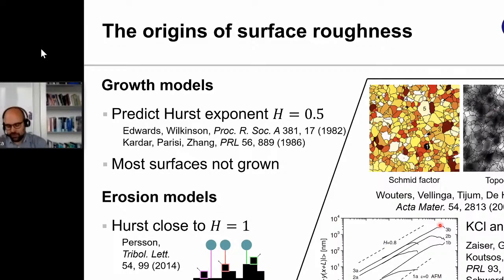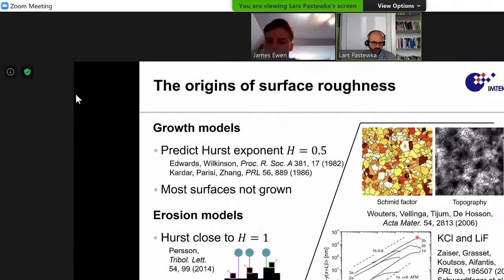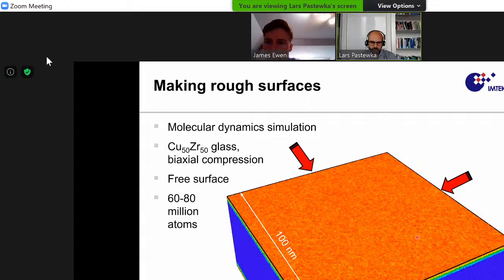So we took these ideas. Michael Zaiser has these experiments and has also done a bit on modeling these systems, but nobody has looked at this before with molecular methods. So we said, why don't we just set up a very simple molecular dynamics calculation? This is a homogeneous piece of material, in this case a copper zirconium glass. It's actually a slab. It has two free surfaces. What you see in red on top is one of the free surfaces, and the other one is at the bottom. And we now expose it to a very simple type of deformation.